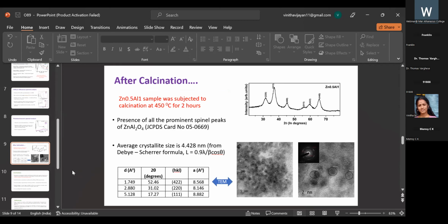Okay, thank you. Why did you choose 450 Celsius as your calcination temperature? Yes, sir. Actually, I had done the TGA DTA analysis before for the sample. But you didn't mention anything about TGA analysis? Sir, actually, that was my previous work, so I have not included it here. I actually have tried 4 different temperatures for the post annealing, and also I had done the TGA DTA analysis. From that, I have fixed this temperature. Okay. Thank you, sir.